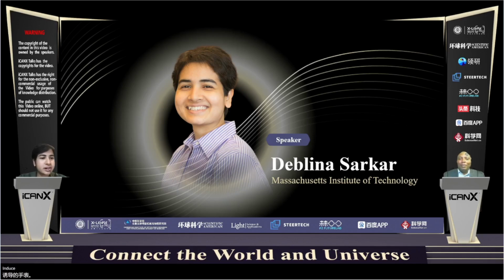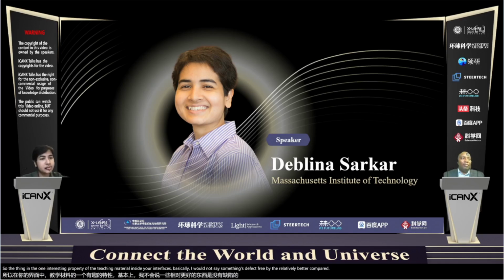Induced what? Sorry. Induced gap states because of the difference in, yeah. So the thing is, one interesting property of the 2D material is that their interfaces are, I would not say completely defect free, but relatively better compared to 3D materials, because between the layers there is no covalent bonding. So their interfaces are saturated, so there are no defect states for the 2D material, but the 3D material still has defect states.